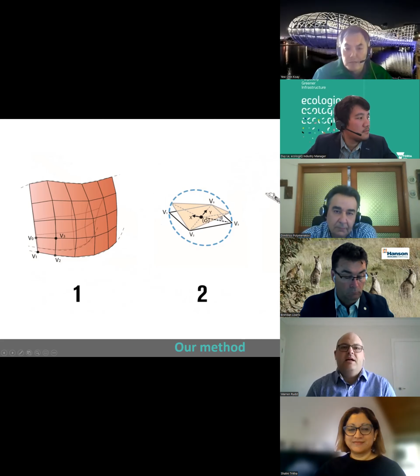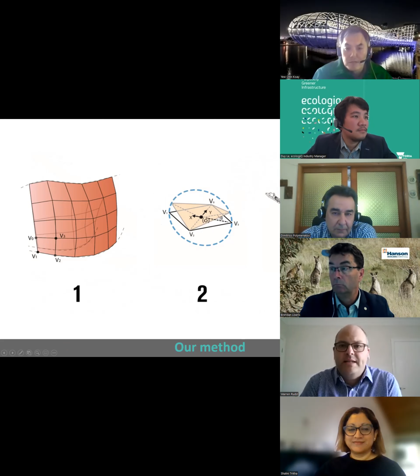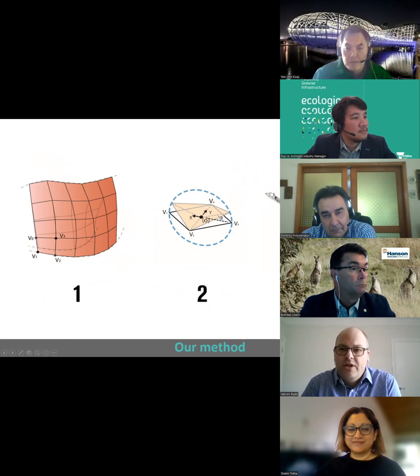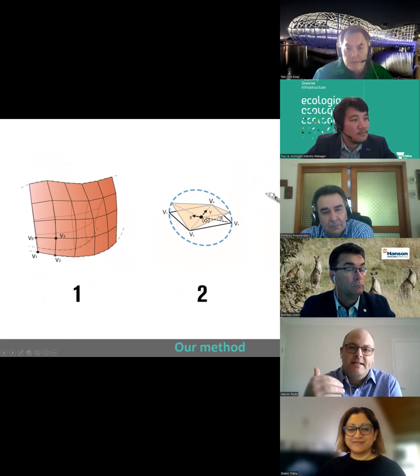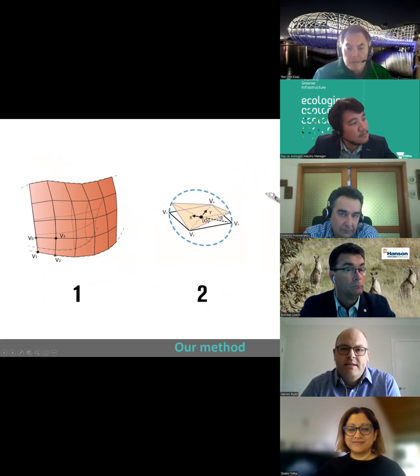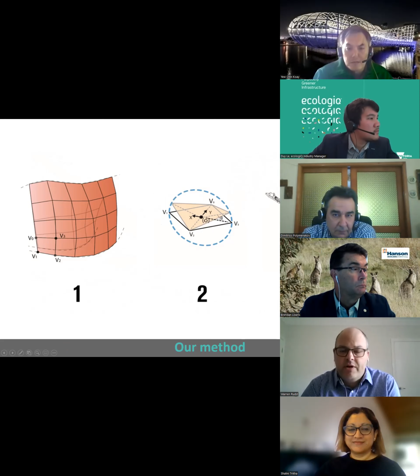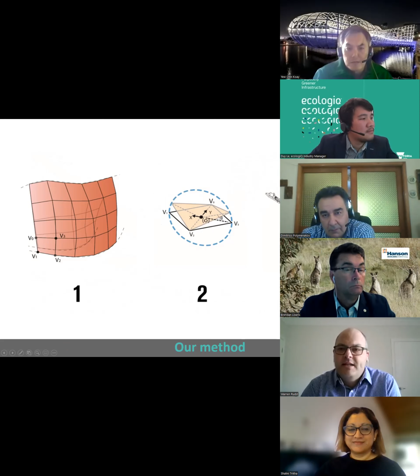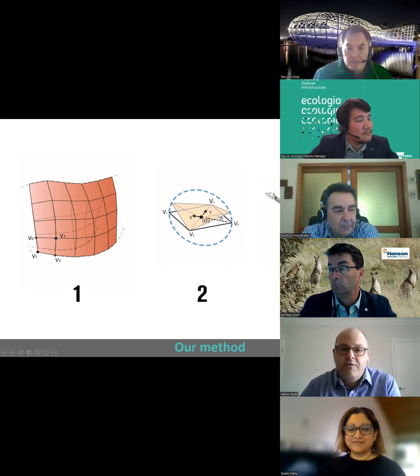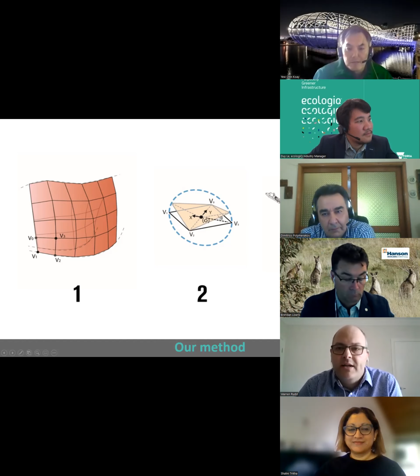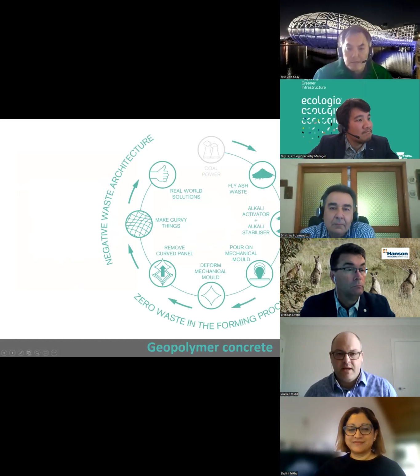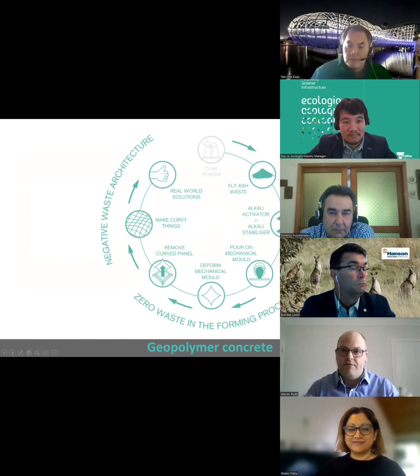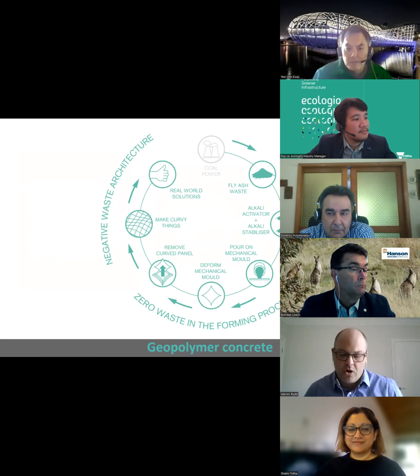So next slide. And how this really works in practice is we've developed a technology that can take a curved design or a free-form design, and it panelizes it, or divides it up into a series of panels. The technology then extracts the geometric coordinates of each of those panels, and it feeds it into our mold. We then cast that panel. Once it's cured, we deform it, take it off the panel, and then we repeat that process without creating any formwork waste. So that was really around the formwork, and then just talking about our low carbon concrete alternative.